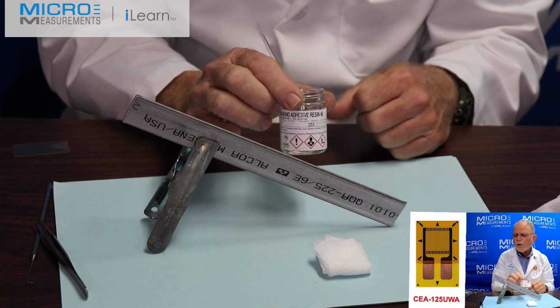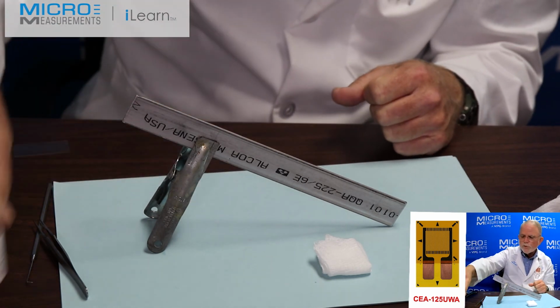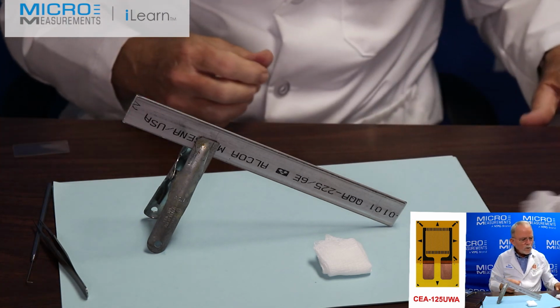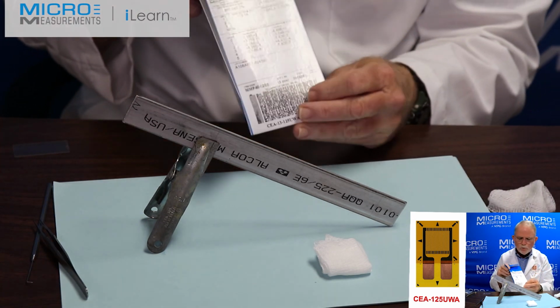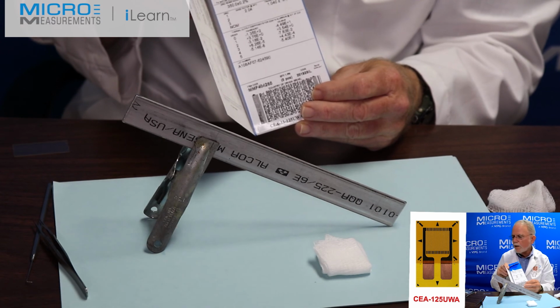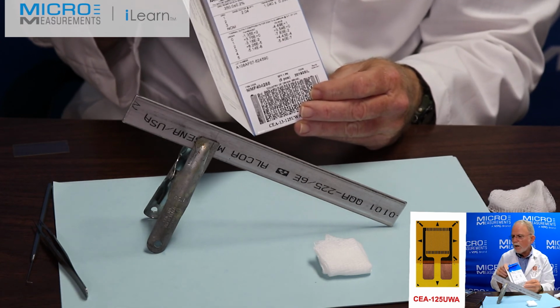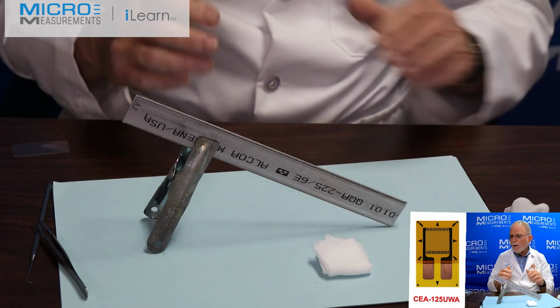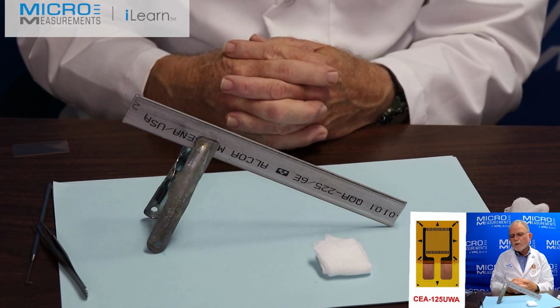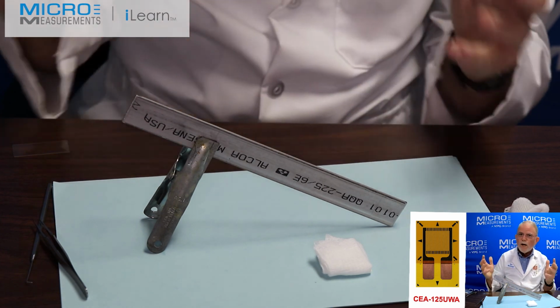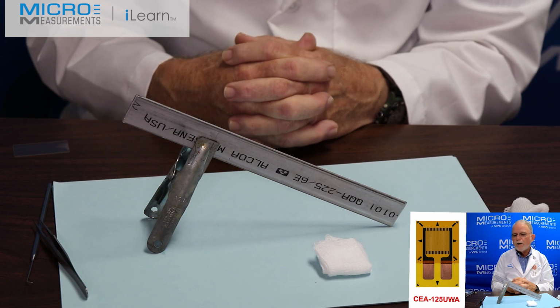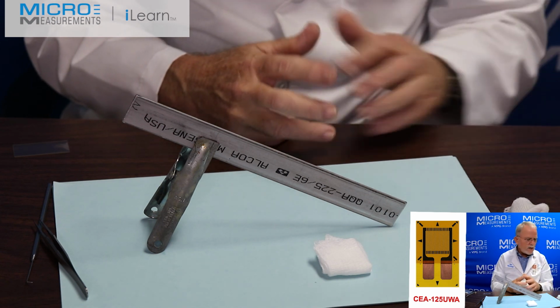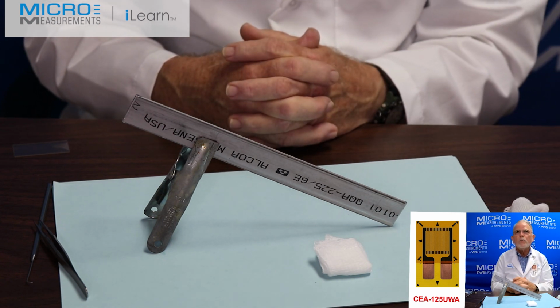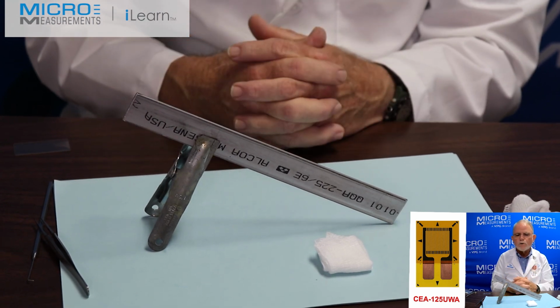minus 320 on the bottom end. It's a room temperature curing. We used a 125 UWA advanced sensor strain gauge to bond it in place. And that pretty much tells you the story of an installation with AE-10, newly highly rated to 400 degrees Fahrenheit, and a CEA series of gauge in the 125 UWA advanced sensor technology.